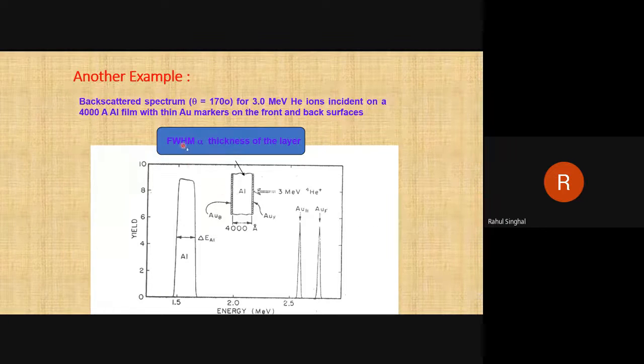Now this tells you how you can find out the thickness. I already told you that the width of the peak is directly proportional to the thickness of the layer. Like here in this sample, we have a 4000 angstrom thick sample, meaning 400 nanometer. On the front side we have gold, gold F means gold on the front side. Gold B means on the bottom side we have the gold, and in between we have aluminum. So we basically have two elements present, gold and aluminum, but the gold layers are at different places. Due to that, we are getting two different peaks of gold.